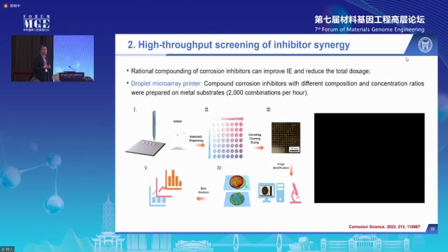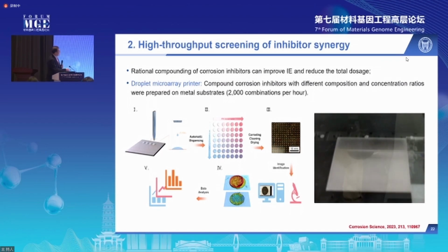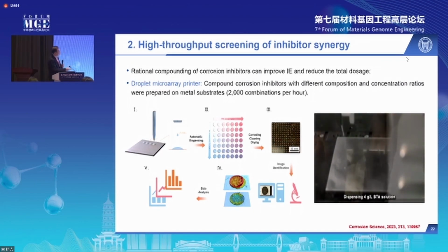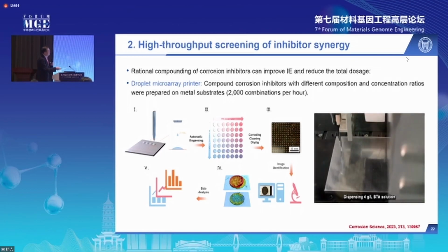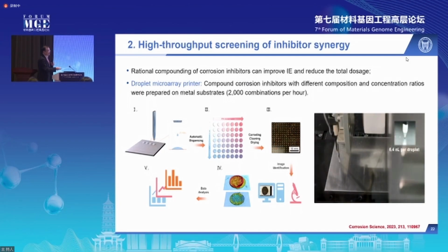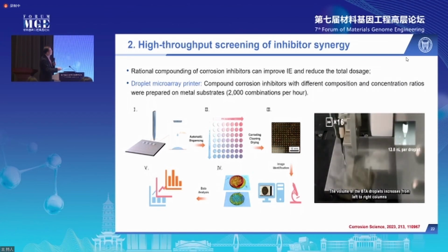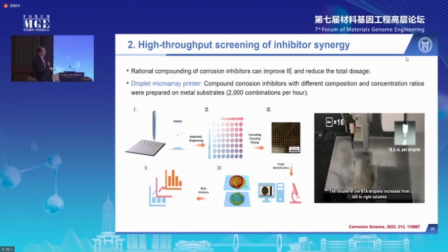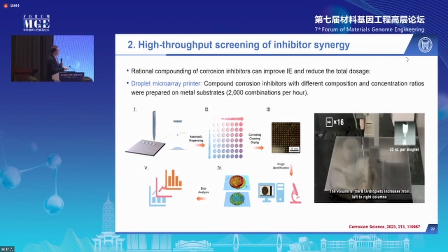So to be able to massively generate a lot of data on inhibitor synergy, we use this type of printing device where the corrosion inhibitor solution droplets are printed and deposited on the surface of metals. For each droplet, the concentration and also the composition of the inhibitor solutions can be very different. And within 1 hour, we can print about 2,000 dots like this.